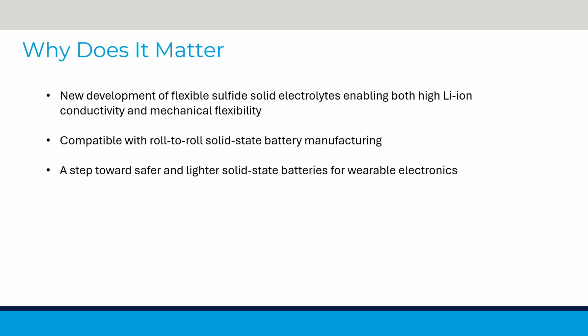This patent demonstrates a practical approach for developing flexible solid electrolytes by combining a rigid inorganic sulfide phase with an elastic polymeric component. This strategy enables easier processing while maintaining high lithium-ion conductivity. Such composite sulfide electrolytes offer an improved balance between mechanical softness and electrochemical performance. The materials and fabrication approach are compatible with roll-to-roll solid-state battery manufacturing and represent a step towards safer, lighter, and form factor adaptive solid-state batteries for wearable electronics.